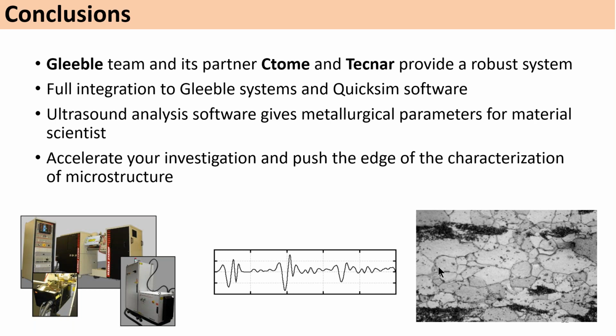After, the little oxide which forms during a Gleeble test is not a problem, as this oxide will be removed each time that the laser fires on it. So I would say oxide scale, it needs to be removed. Oxide during Gleeble test is not a problem.